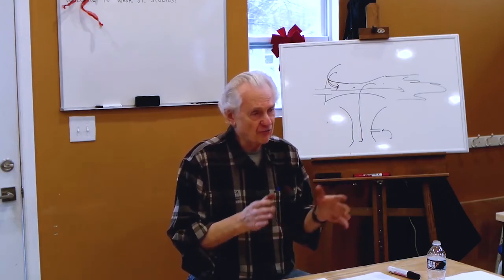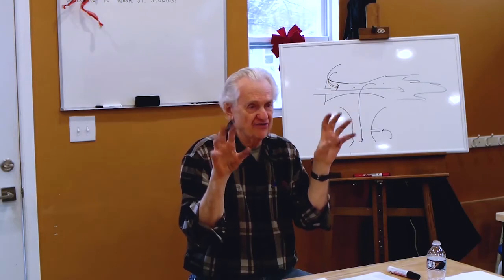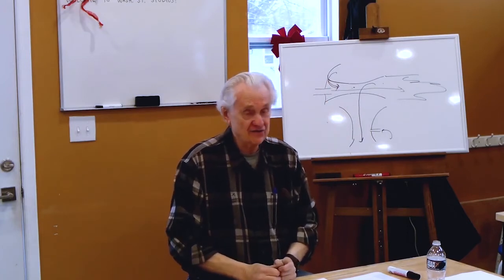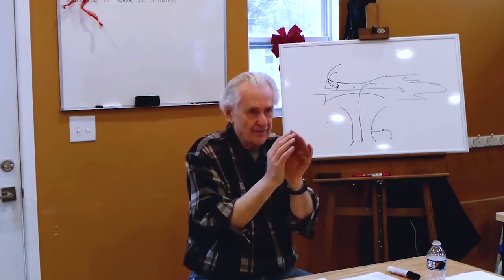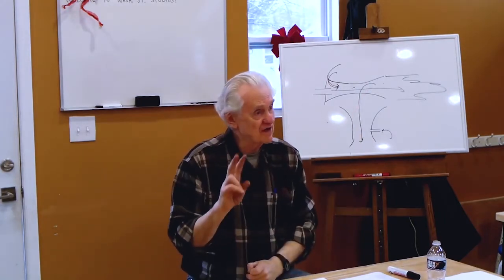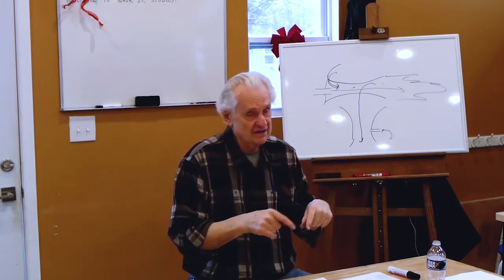We've made the ash glazes runny, but they also have a high surface tension, meaning that the liquid wants to pull itself into itself, which is why it pulls itself into streams, and then the streams flow. So the high surface tension makes the glaze attract to itself and want to stick together, but the fact that it's runny makes it flow. So instead of getting sheets of glaze, we get streams of glaze. And we take advantage of the balance between those two properties, the surface tension and the viscosity, to create the effect that we like in ash glazes.